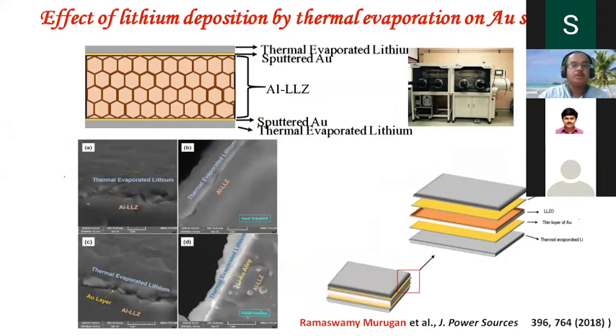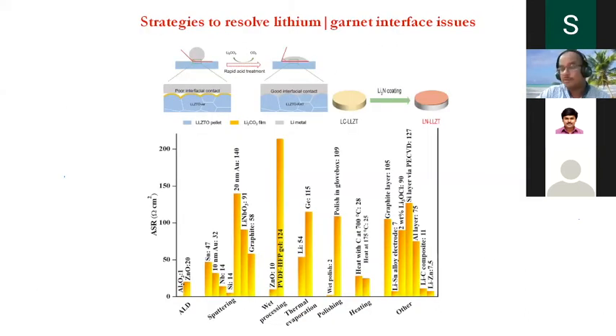This is our earlier research. We were able to put a small layer of gold between the metallic lithium and the lithium garnet. It's what we call thermal evaporated lithium. There's a large gap when you put this. But when you put the gold layer and sinter it, I could see a gold-lithium metallic alloy formed, which helped a lot to reduce the interfacial resistance. At the same time, it improved the critical current density, which helped a lot to overcome dendritic growth.